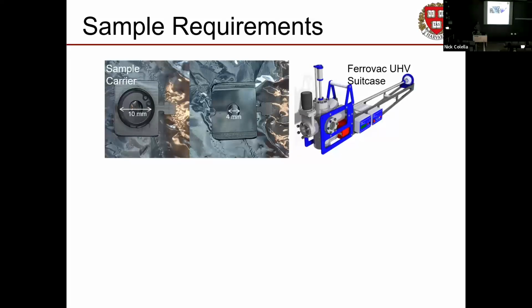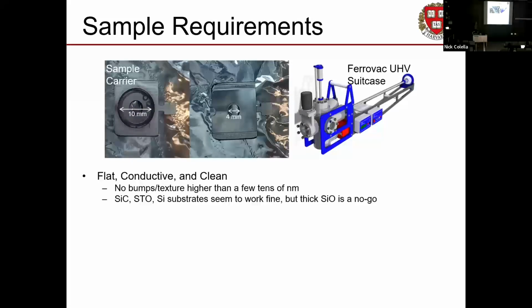But okay, we have mounting tricks to make this work if your sample doesn't fit in those sizes. If the sample is smaller than 4 millimeters, you've got mounting tricks. If it's bigger than 10 millimeters, I've got half size. No worries, make it work. Your sample needs to be flat. It needs to be flat because if it's not flat and we put 15 kilovolts on it, you're going to get diverging field lines coming off all the bumps, and your electrons are going to get bent off to the side, and they're not going to go back up through the lens, and we're not going to get a picture.